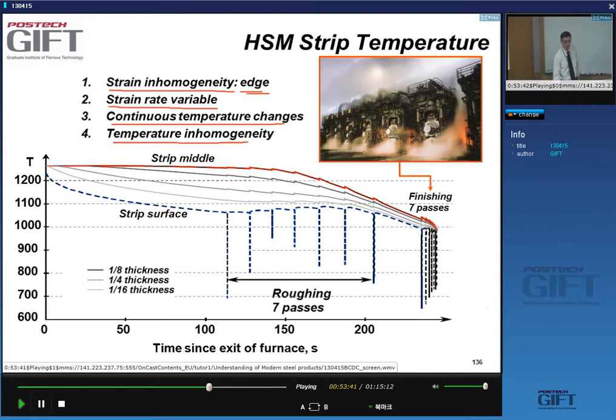So if you look at the temperature of the strip as you go through the mill, this is the time here, time from exit of the reheating furnace, yes? You see, of course, that this is the temperature at the surface, and then below the surface at 1/16 of the thickness, 1/4 of the thickness, and here is the strip middle, yes? And what you see is that the strip middle cools down at a much lower rate than the surface, yes? And there are other things that are different, is that every time the strip surface touches a roll, yes,